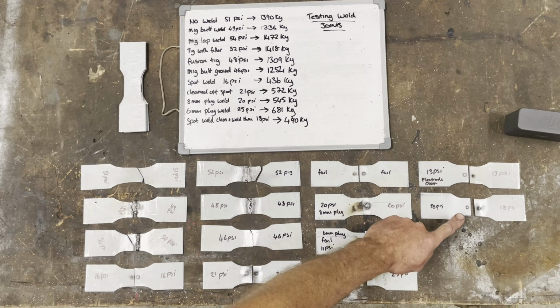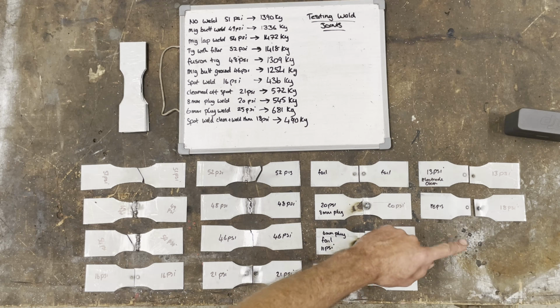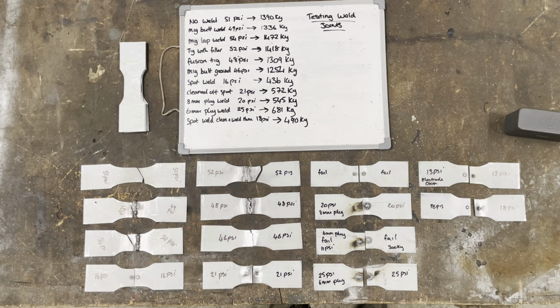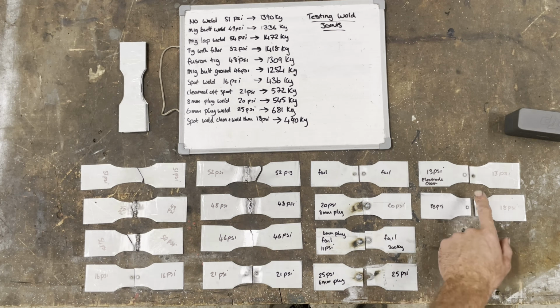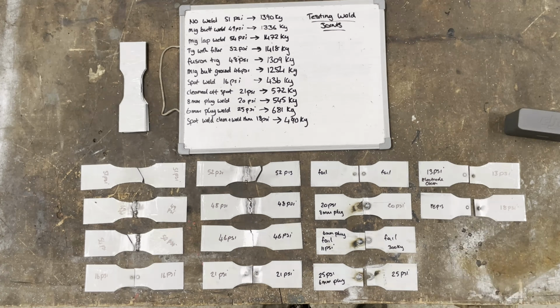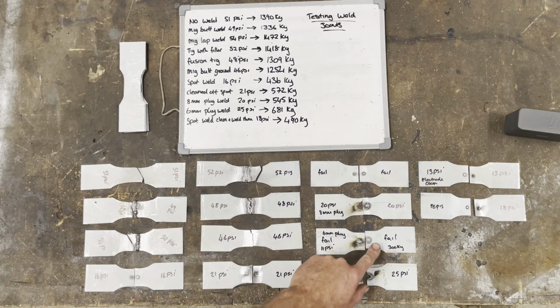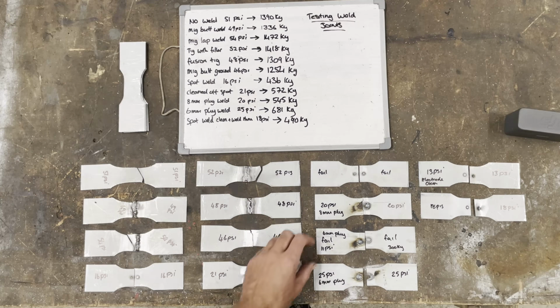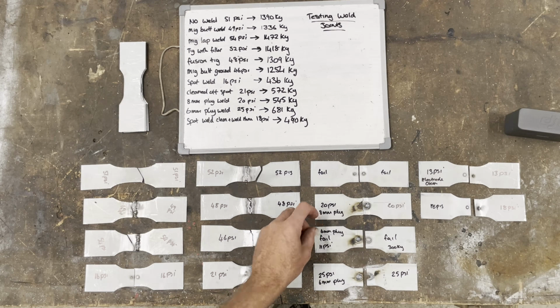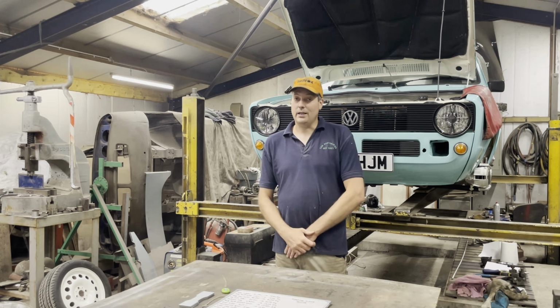The zinc-rich weld-through primer does affect the strength slightly, which you would expect, but we have to have something between two bare metal sheets, otherwise it's going to corrode. You'll see some top-end restorers advertising that they don't grind their welds, and that's because it keeps the strength there. Well, there isn't much difference, is there? When you are plug welding, make sure you've got these amps nice and high, otherwise you could have a failure like that one. Well, I thought that was quite interesting.